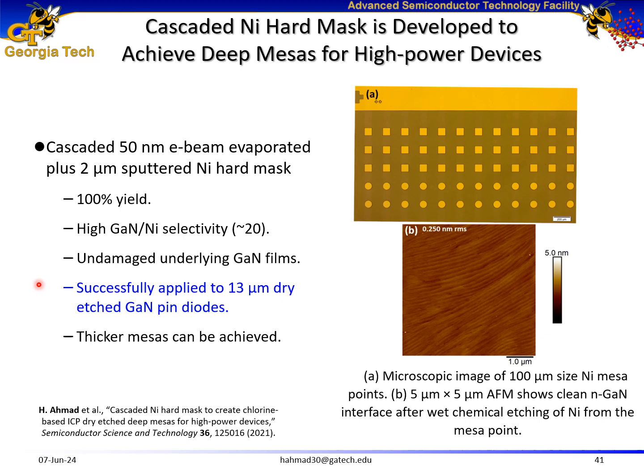So finally, I devised a novel procedure of nickel hard mask in which I first deposited 50 nanometers of E-beam evaporated nickel followed by 2 microns of sputtered nickel. It resulted in 100% yield, high gallium nitride to mask selectivity, undamaged underlying films, and I was able to successfully apply it to my thicker actual gallium nitride pin devices. And with this technique, we can also achieve thicker mesas.